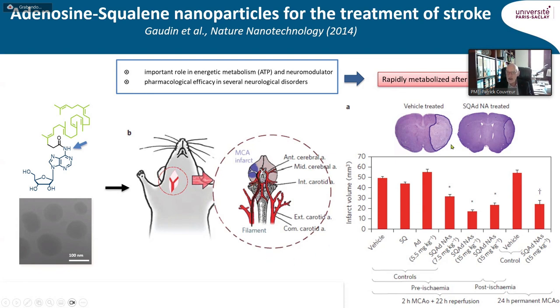And this will induce, as you can see here, an infarct volume. And you can see that after administration of adenosine as a free drug, there was absolutely no diminution of the infarct volume comparatively to the only vehicle-treated animals. But after the administration of the adenosine squalene nanoparticles, either here pre-ischemia at 2 doses, or even post-ischemia, or even after 24 hours permanent occlusion, you can see that there was a very strong diminution of the infarct volume, and clearly we provided a very dramatic neuroprotection.